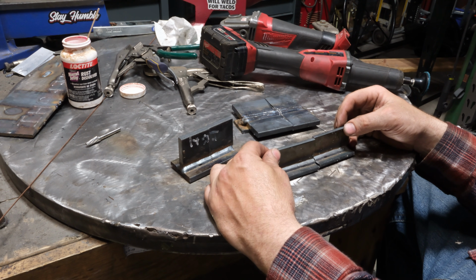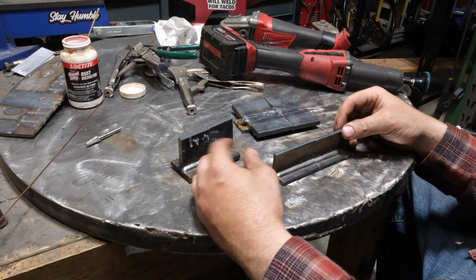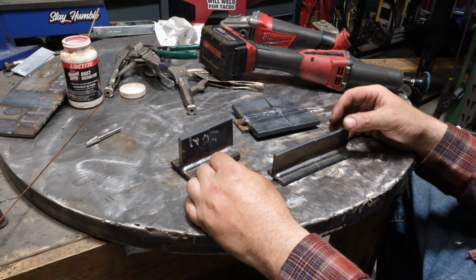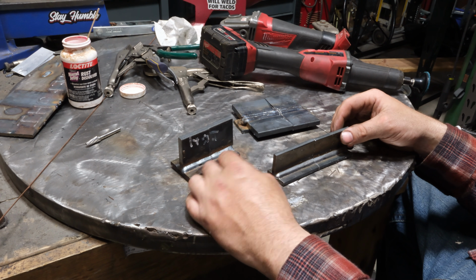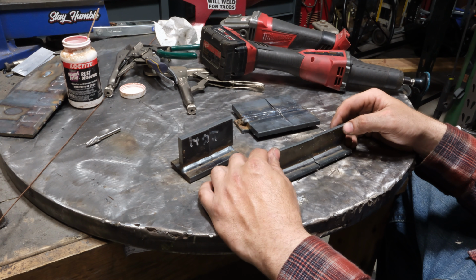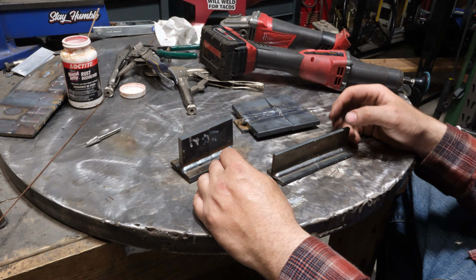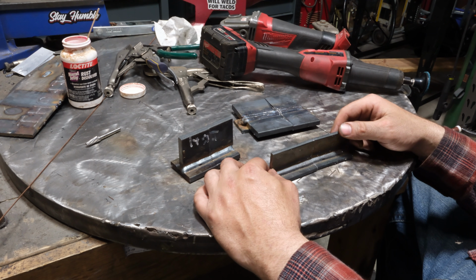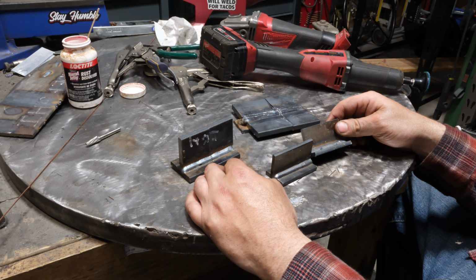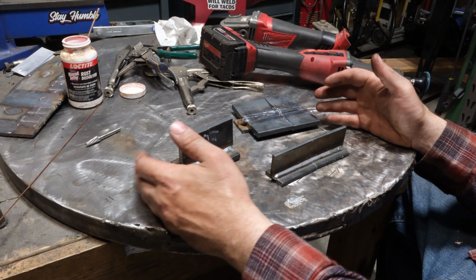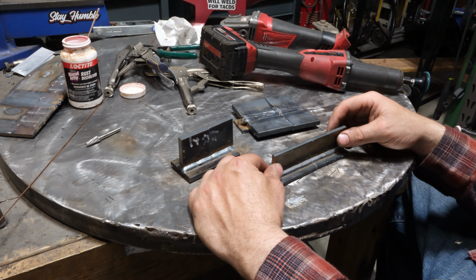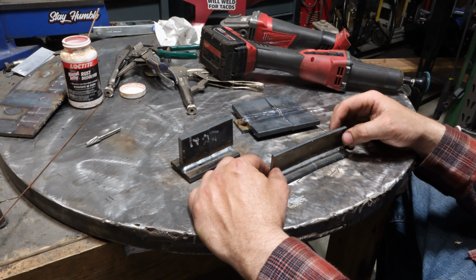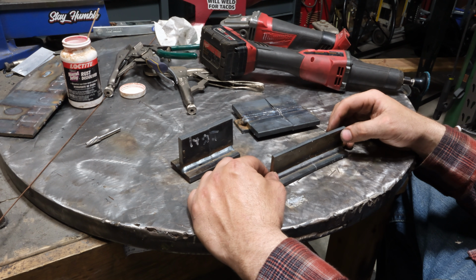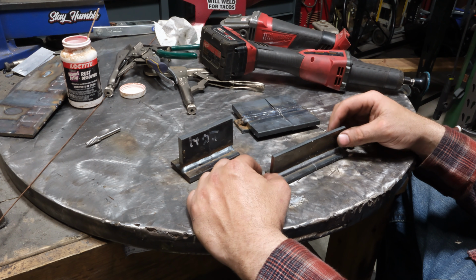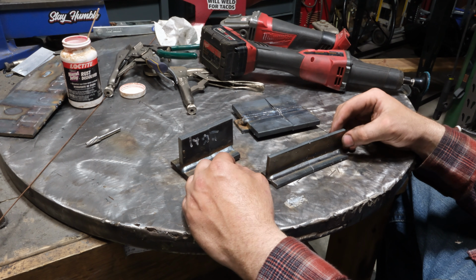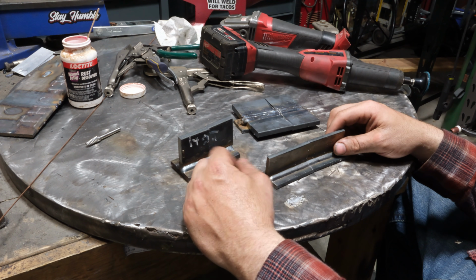And like I tell everyone in the comments, 1/4 inch plate for the short circuit MIG process, provided you have a 200 to 225 amp legit capable machine, is really no issue. And in a lot of cases, this would provide more root fusion, or penetration, than stick with 7018. The difference, though, keep in mind, is this is perfectly clean steel. This is the ideal circumstance. Where 7018 is going to come out ahead is when you're welding on crusty, rusty stuff. You're going to start getting weld defects and porosity and other issues with the short circuit MIG over stick. But for clean metal, it's more than adequately strong enough and penetrates perfectly fine, as you saw.